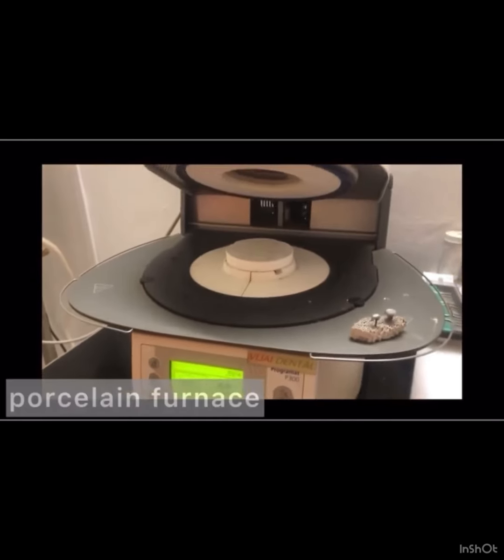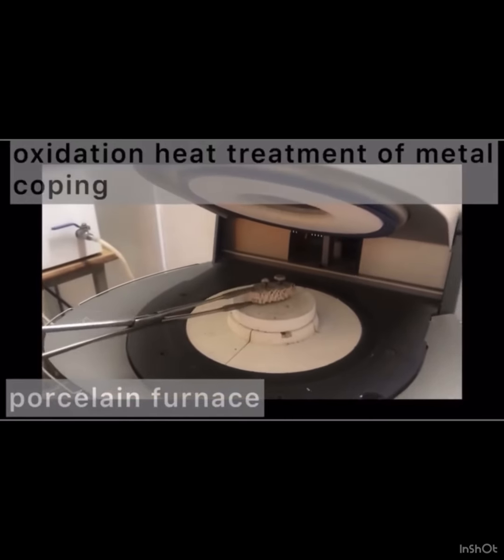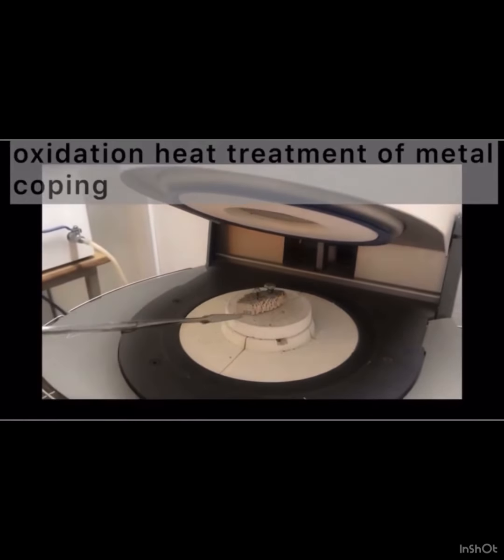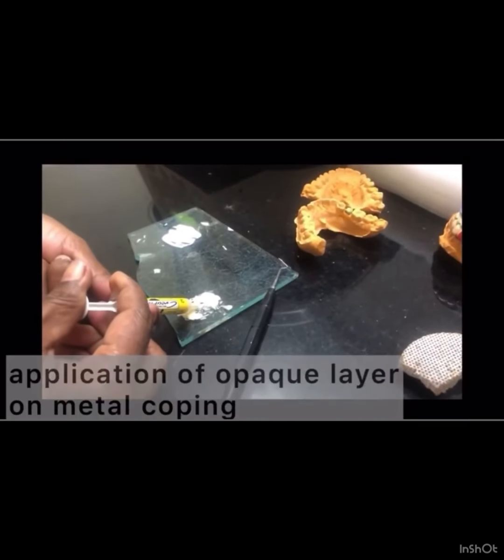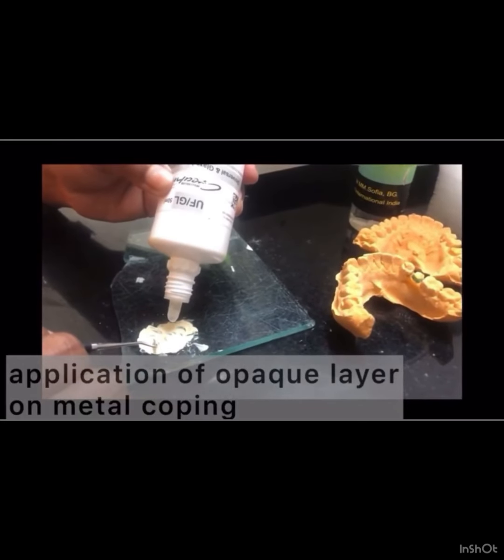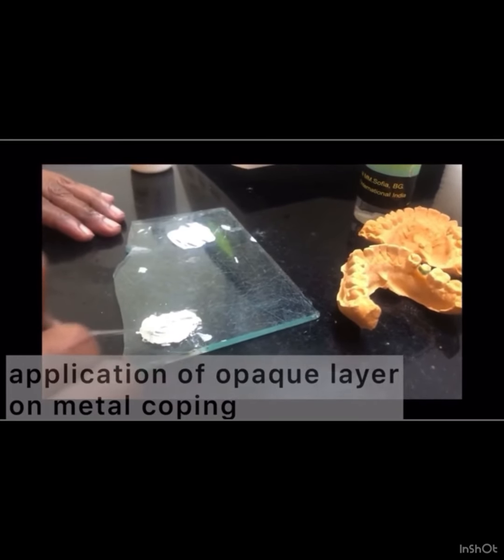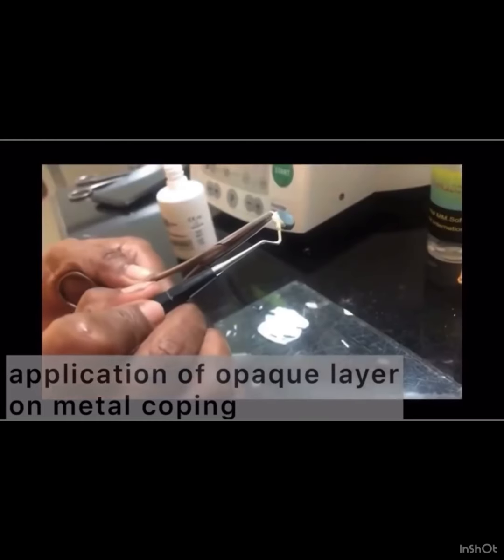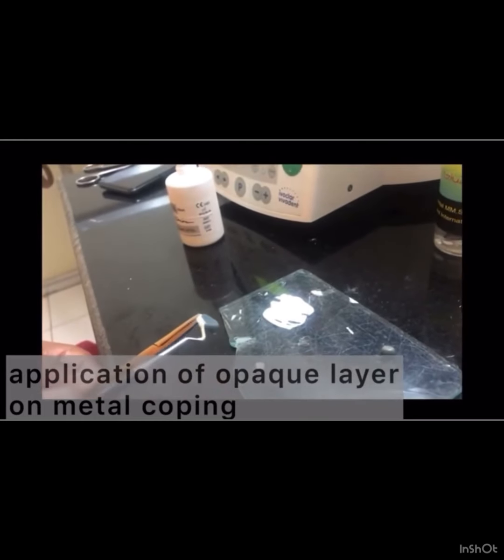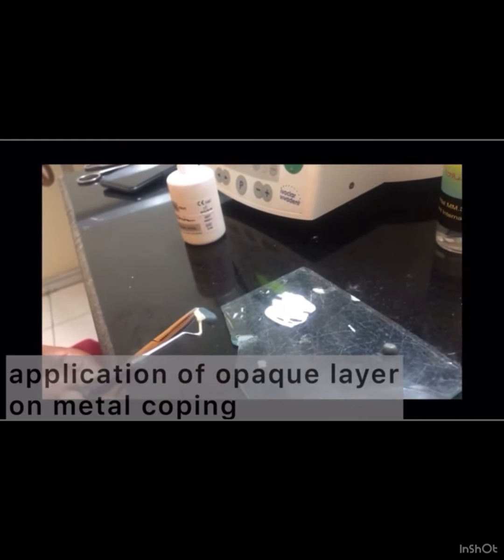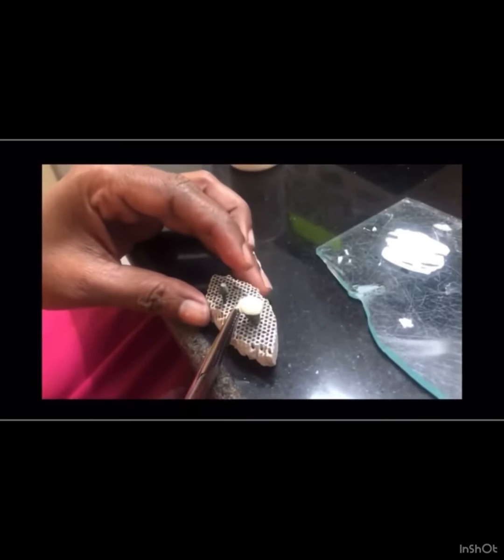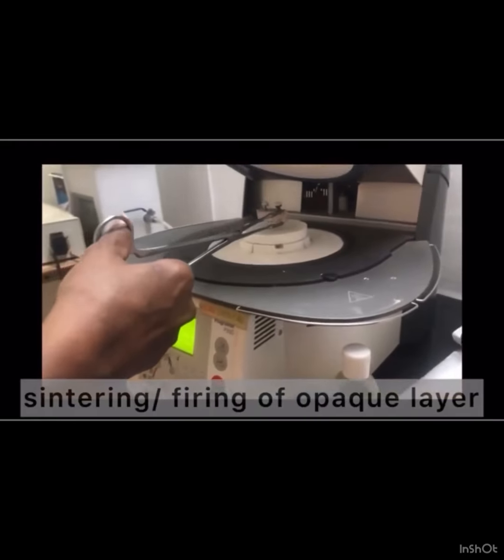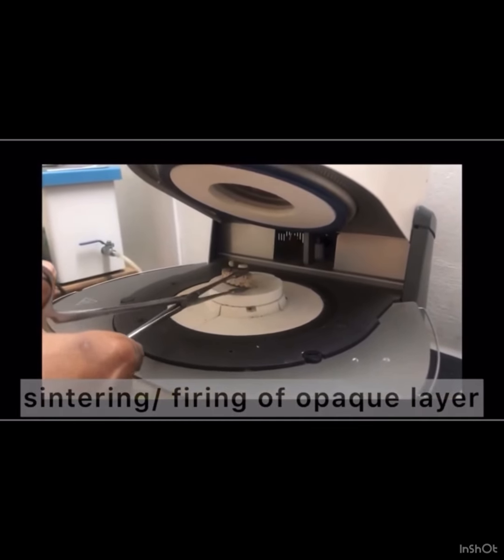Here you can see the porcelain furnace. In the beginning, the metal alloy coping which we obtained after casting is placed in it for oxidation heat treatment. This leaves a thin layer of metal oxide on the surface which improves the metal ceramic bond. Porcelain is condensed in layers. First is the application of an opaque layer. The powder and liquid are mixed together and it is applied in a thin coating over the coping. After applying the opaque layer, it is placed in the furnace for sintering.